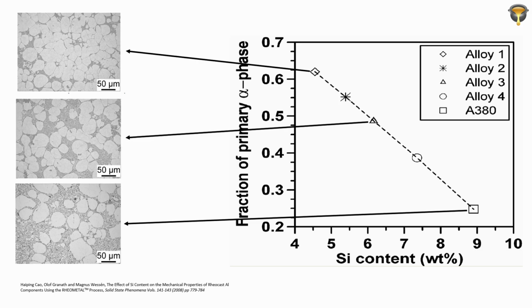If you look at the graph like this, you will say that 8.5%, no way, you will not have enough solid fraction. But if you're looking at an A383 or 226 or 46,000 and place them inside the specification and cast with Rheo, there are so many other additives in the alloying elements like iron, manganese, magnesium, etc. And all these different atoms help to expand the process window.